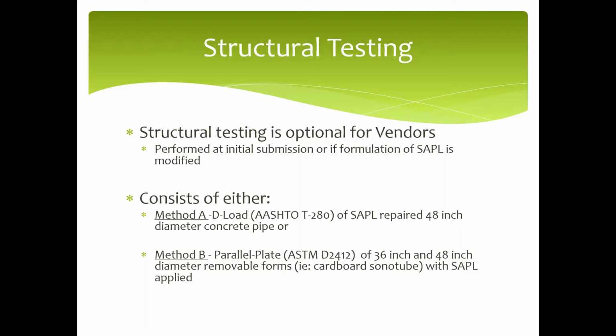So we have two different methods: Method A and Method B. Method A is simply a D-Load test where we take a 48-inch reinforced concrete pipe and crack it in the D-Load test initially, just a bare pipe. Then we have the vendor come in and apply their liner in different thicknesses, we let it cure, and then we come back and do another load test, and that will show us if we have an increase in capacity or not.